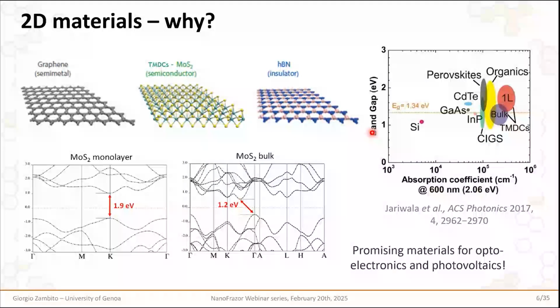And also, another peculiar aspect of these materials lies in the fact that they possess an electronic band structure that is dependent on the number of layers that you consider. So, for example, for molybdenum disulfide, which is probably the most known and most studied semiconducting transition metal dichalcogenide, you have a direct to indirect band gap transition when you go from a single layer to a two or more layer configuration. And also a quantitative dependence of the value of the energy band gap, depending on how many layers you consider. So there are a lot of possibilities to tune and exploit these materials, which possess, among all their properties, this kind of interesting behavior.